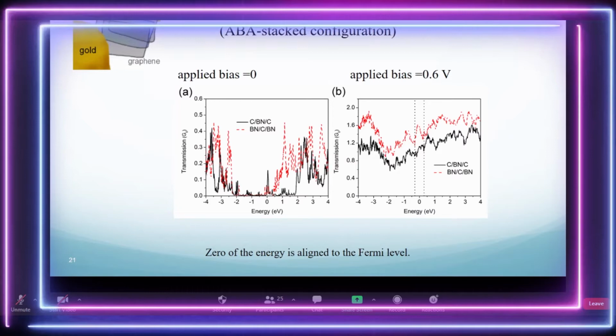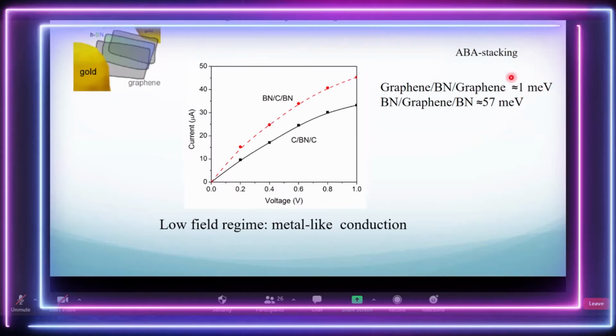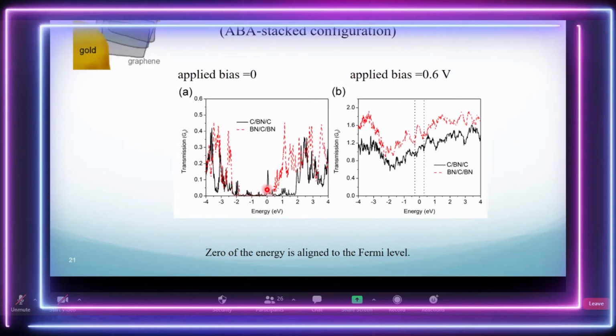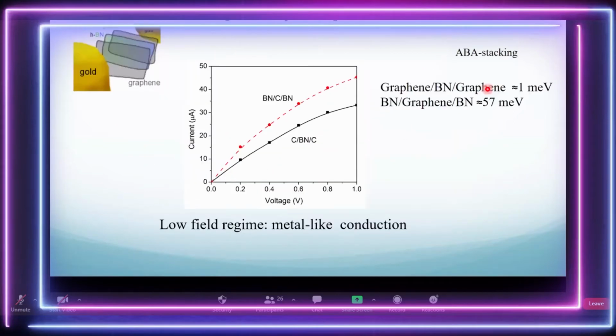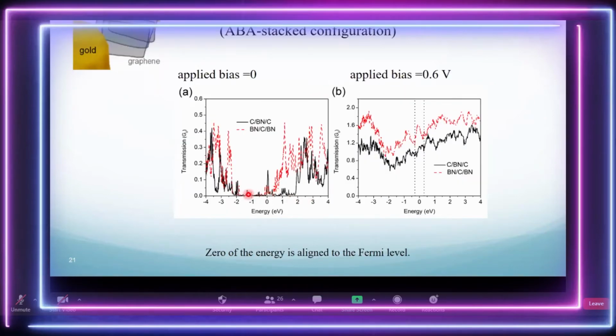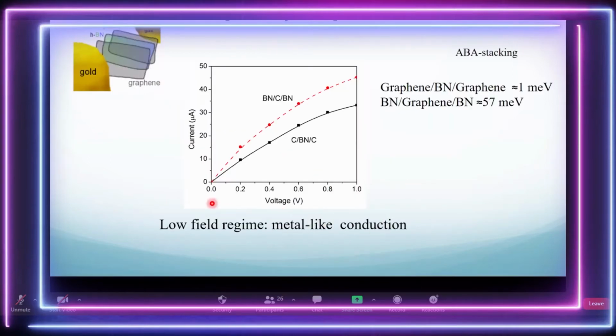So what you expect, with no bias, if you don't apply any electric field, is this. The black one is the first case, where boron nitride is sandwiched in graphene. And for this case, we have zero gap, hardly any gap. And you can see indeed there is a finite transmission function, or density of states if we may call it, around the Fermi surface. It makes sense. But if you look at the other case, where we have a larger gap, what you find is, yes, it's true, there's a gap here. But if you apply the electric field, because of the shifting of these states, both cases have a finite transmission function near Fermi. And this is why we have metal-like conduction for both cases.